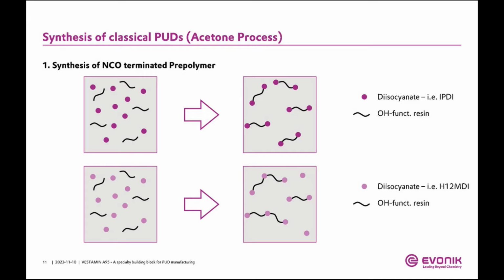So this is an unwanted reaction. You don't want to emphasize the chain elongation for this viscosity reason. And of course, if you have more chain elongation, you will also have unreacted monomers, which give you problems with toxicity, of course, of your prepolymer. So both effects want to be avoided, and that's the reason why you want to go for the above picture, where you have the most selective synthesis possible.